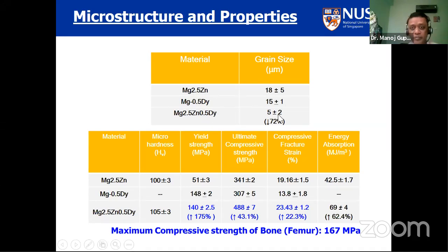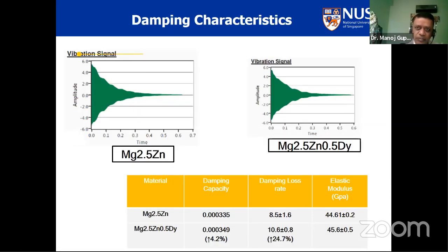Microstructure is good with only 5 micron grain size, much better than the other two compositions. If you look at the yield strength, it's higher than 2.5 zinc, similar to the dysprosium alloy. And if you look at the UCS, it goes up. But anyway, all these properties are superior to that of bone, and we have a wonderful ductility, so this material is very, very tough. So we are okay from the mechanical properties.